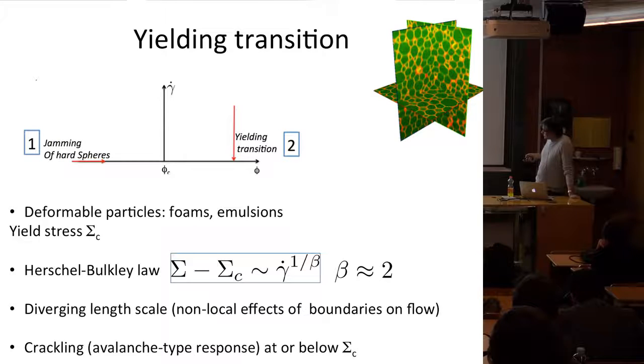Something else which is interesting is that if you're right at sigma c or slightly below, so you're in the solid and you drive it quasi-statically, you see plasticity with an avalanche-type response. Sometimes you have small rearrangements, and sometimes you have very big ones. But I will come back to that.